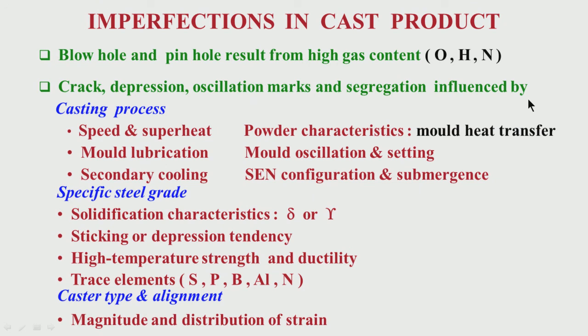You cannot escape segregation, but you have certain controls so that the segregation level is relatively less. Some continuous casting parameters will lead to less segregation. All these defects — cracks, depression, oscillation marks, segregation — are dependent on three major issues: first, the casting process itself; second, the specific steel grade; and third, the caster type, such as whether it is a vertical mold or curved mold, and what is the radius of the caster.